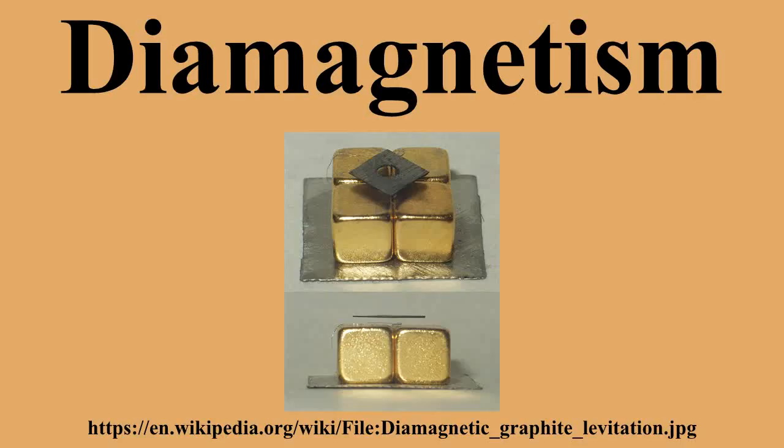Levitation. Diamagnets may be levitated in stable equilibrium in a magnetic field, with no power consumption. Earnshaw's theorem seems to preclude the possibility of static magnetic levitation. However, Earnshaw's theorem only applies to objects with positive susceptibilities, such as ferromagnets and paramagnets. These are attracted to field maxima, which do not exist in free space. Diamagnets are attracted to field minima, and there can be a field minimum in free space.